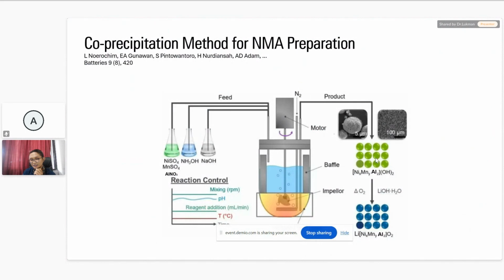So we are in 2023. Last year, maybe before that, we started to synthesize this cathode, NMA. We call it NMA; people also know this one. Using a method similar to NMC preparation, we use nickel sulfate and manganese sulfate, and we replace cobalt sulfate with aluminum nitrate, using chelating agent ammonium and then sodium hydroxide. We use this kind of apparatus in a big tank to prepare the NMA product.